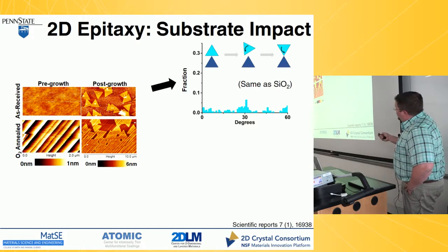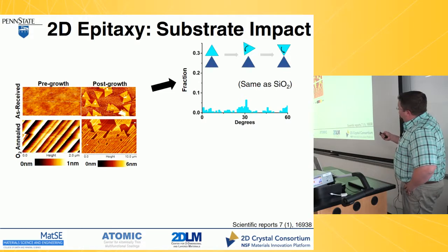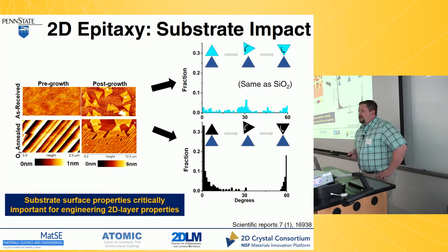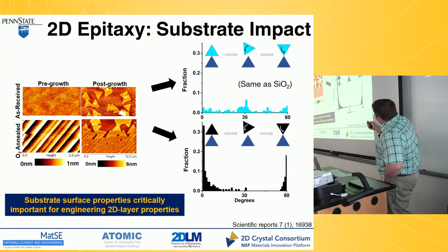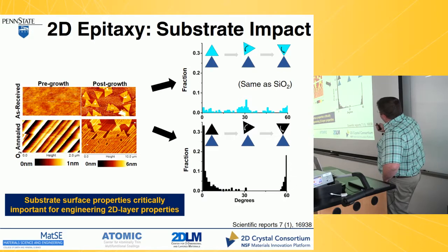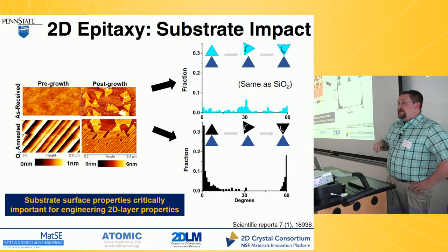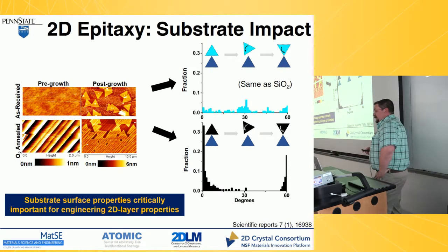And in fact, if you look at this, here's the non-coalesced to a coalesced region. They kind of look like they're oriented there. And in this non-coalesced region, you see, in fact, that most of them are in one particular orientation or the other. They're either in the same direction or in opposite directions. It's because this is crystallographically equivalent, because it's threefold symmetry, to the substrate underneath.